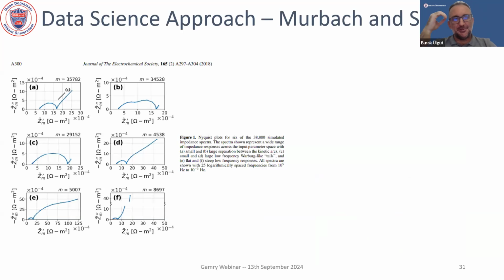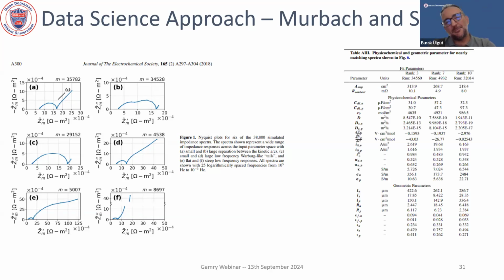Okay. Now, this thing actually started with, again, another talk. This was at the ECS meeting, I believe, in Seattle, since Matt Murbach was a student there under the supervision of Dan Schwartz. So what they did was they took a battery model, a model from Newman, Doyle-Fuller-Newman P2D type model, for those of you familiar with it, and they simulated spectra that are directly out of a fundamental model with all of these parameters that you see on the right. So capacitances, concentration of the electrolyte, diffusion constants, kinetics, self-exchange rate constants, transfer coefficients, conductivities, thicknesses, dielectric constants, whatever, okay?